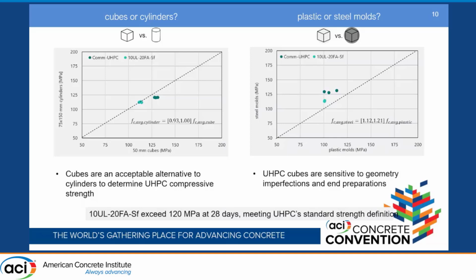Also, when you test UHPC, usually standards refer to cylinders, and we got our results on cubes. Cylinders have the challenge that they require high load capacity machines that not all the labs have available. So we said, okay, with what we have, let's see if we can run a comparison between cubes and cylinders. And actually we saw that cubes are an acceptable alternative, because there was a nice correlation between the results of these two specimen geometries.